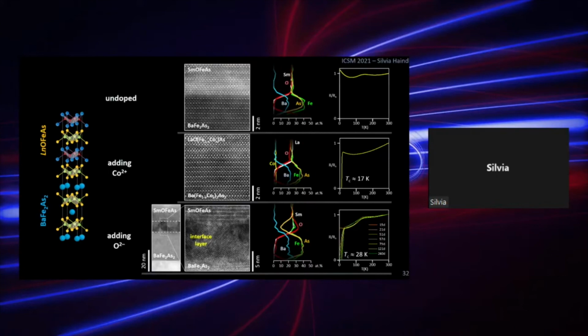In the case where we have the oxygen imbalance, we find an interface layer here, and we also find this induced metal to superconductor transition. You can see here in this graph of the resistance versus temperature that it becomes superconducting after 50 days. So this is quite long, a quite slow diffusion process, if there is a diffusion process. So we don't know exactly what is diffusing into it and induces this superconductivity. Films were stored in a normal desiccator, and some films were stored in air, and both show the same result. So the storage is not the difference.